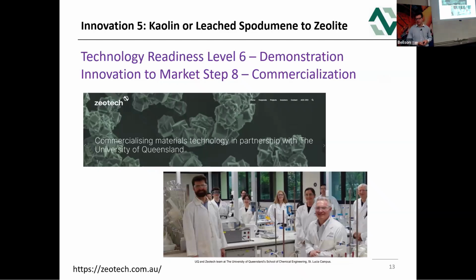A fifth innovation was around converting a low-cost feed like kaolin or leached spodumene into a high-quality zeolite product. Hong Peng is a senior researcher here who led this project. We came up with the technology, went through UniQuest, and came to an agreement with the company, who then rebranded as Zeotech, and we piloted this, building up to a continuous pilot at the Long Pocket facility for about 6 months. We produced 25 kilos of high purity zeolite from leached spodumene and clay starting materials, and demonstrated the technology. So it's technically feasible, and it's still a potential pathway that could be brought to commercialization.